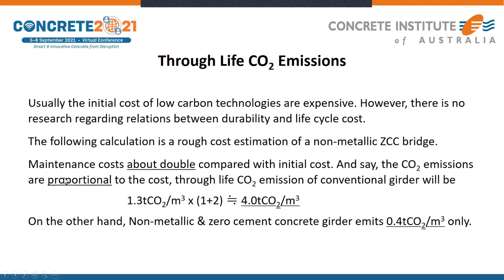As I said before, the highway companies' engineers said the maintenance cost is about double compared with the initial cost. So I use this value and say the CO2 emission is proportional to the cost. I already confirmed that this is proportional. Through life CO2 emission of the conventional girder will be 1.3 tons times 1 for initial, 2 for maintenance, around 4 tons CO2 per cubic meter. On the other hand, the non-metallic zero cement concrete girder is 0.4, with no maintenance emission.